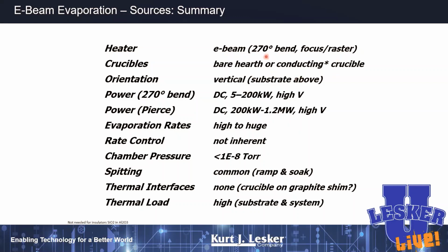And typically, if you want to do conductive materials, you've got to use a conductive crucible, like copper or tungsten or pyrolytic graphite. We're going to always E-beam up. The power supply parameter is a little bit different here. Your evaporation rates are massive, but you don't have much control over it.